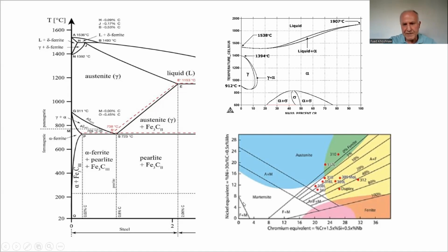If you have both of them, then duplex stainless steel appears, which is ferrite and austenite in between. So this is fully ferrite when chromium is high. When nickel is high, austenite is the predominant, but in between, that's duplex stainless steel, 10%, 20%, 50%, and so on for each. Why are we saying that? Because when we have two different phases, austenite and ferrite, same as here, ferrite and cementite, this cementite acts as cathode compared to ferrite. So there will be a galvanic action in every grain, and that somehow causes pitting, and at the end causes somehow general corrosion on steel.